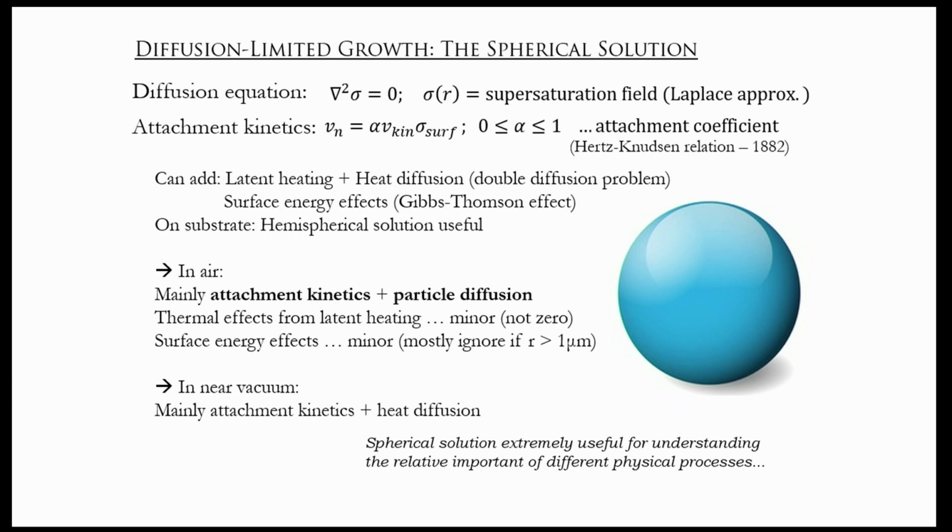And so we put a lot of physics in that alpha term, because alpha does depend very strongly on sigma. So really we've just changed variables. We've taken velocity as a function of sigma surf and just written it this way, separating out one term of sigma surf, just a well understood number, and then put all the physics in alpha of sigma and T. Okay.